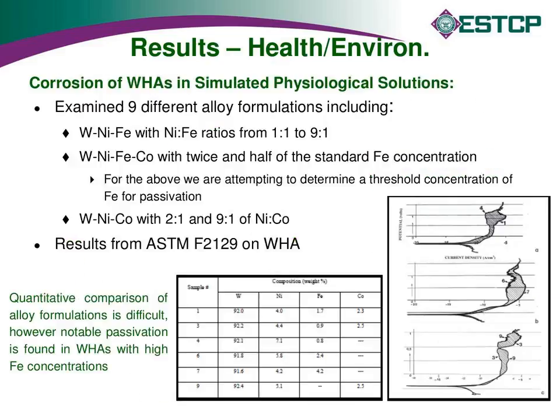We did some work trying to adapt some standard assays that were used for medical implants. We did some others just looking at the simple corrosion and analyzing what was coming out in solution in phosphate buffered saline. What we found with the standard ASTM F2129 on tungsten heavy alloys is that it doesn't seem to be a good screening test for those materials. That's meant to screen materials that are engineered to resist corrosion in the body. And so whether these alloys cause cancer or long-term health effects, they corrode either way. Whether that corrosion is through galvanic cell corrosion or through passivation with the oxide formation, this just isn't an ideal screening method.